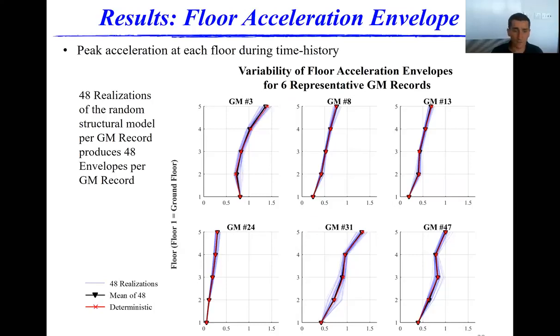And we also can note that for some of these ground motion records, the model parameter uncertainty seems to play a relatively small role, particularly for, say, ground motion 24 or ground motion 8. We're not seeing a whole lot of variability on the EDPs just from model parameter uncertainty. But for other ground motion records, say, for example, ground motion record 31, we see a lot of variability on the second floor's peak floor acceleration. So this could indicate that in some instances, model parameter uncertainty can have a tremendous effect, and other times it has a negligible effect. And the purpose of looking at plots like this is that you are isolating the effects of model parameter uncertainty. So you're cutting out record-to-record variability for each of these plots. This is just the uncertainty due to the model parameter uncertainty.